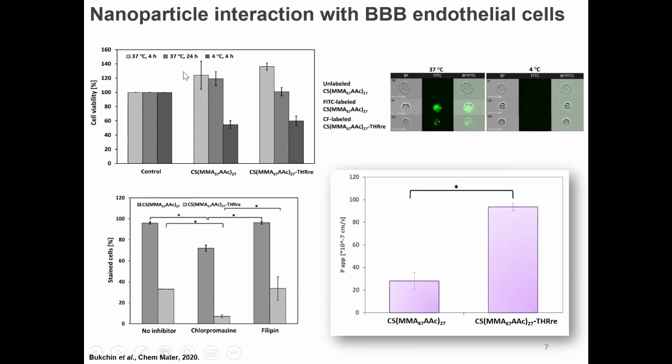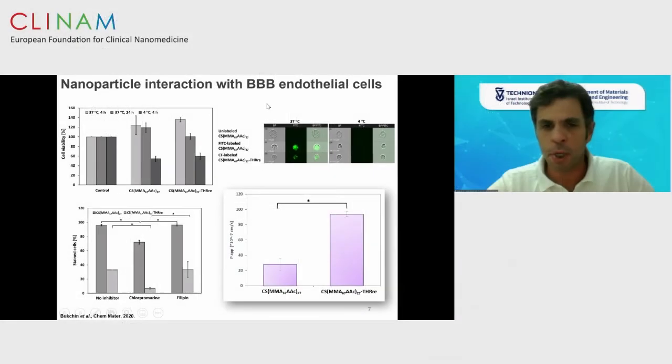We demonstrated that at least for 24 hours at 37 degrees, these nanoparticles are quite cell compatible. We observed a decrease in cell viability at 4 degrees, which was used to characterize the internalization under conditions that prevent or minimize energy-dependent pathways. So this is what you see here.